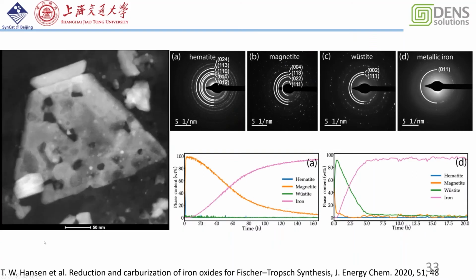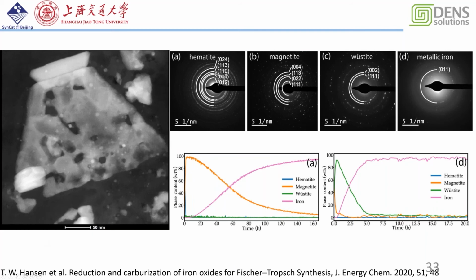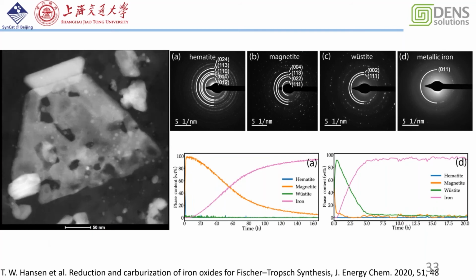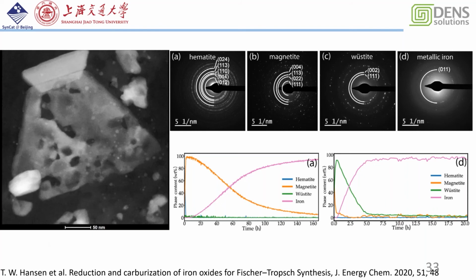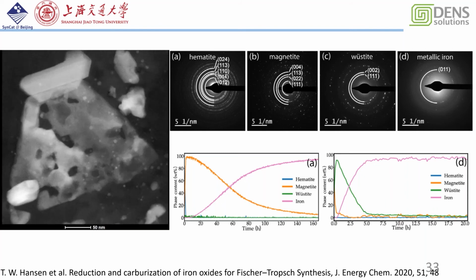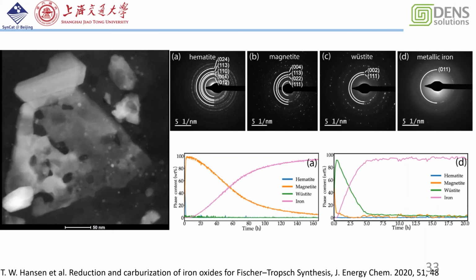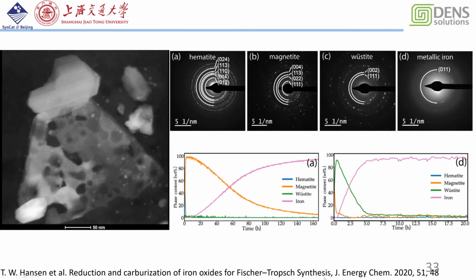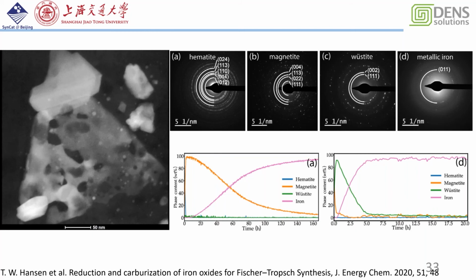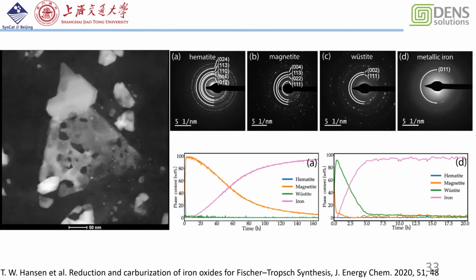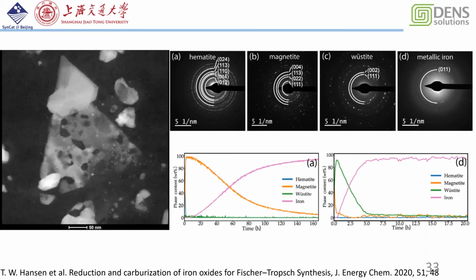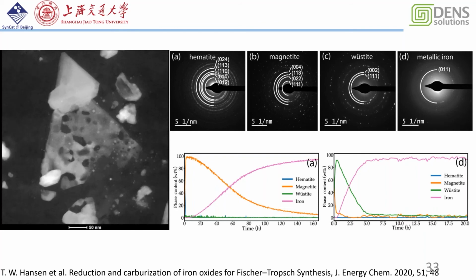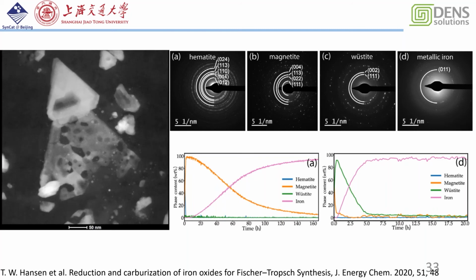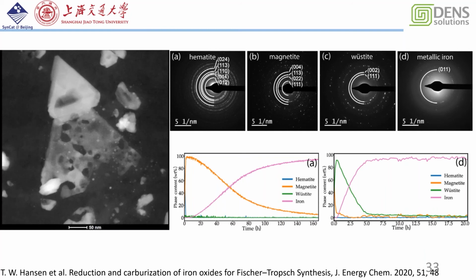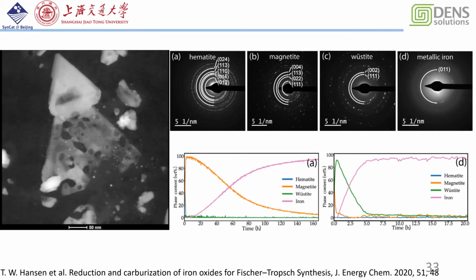But when we increase the temperature even higher, to almost 900 degrees, we see the formation of the metallic iron. But still, the magnetite is very difficult to reduce. In collaboration with Thomas Hansen, we do both the in-situ electron diffraction technique and in-situ TEM, in-situ XRD technique. And we found the reduction process is really difficult below 900 degrees. We really need an extremely long time to get complete reduction. But what hinders the magnetite reduction to metallic iron is still not clear.